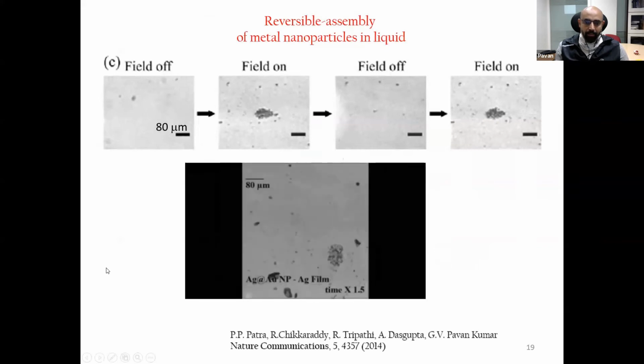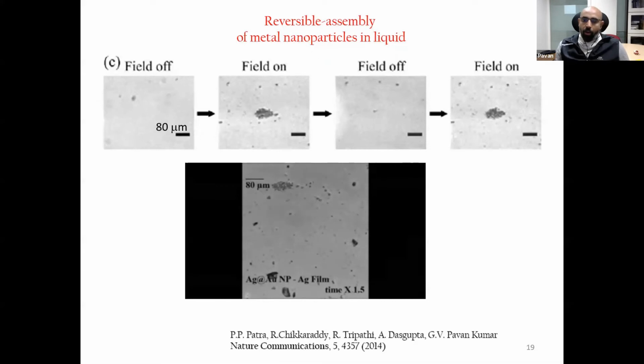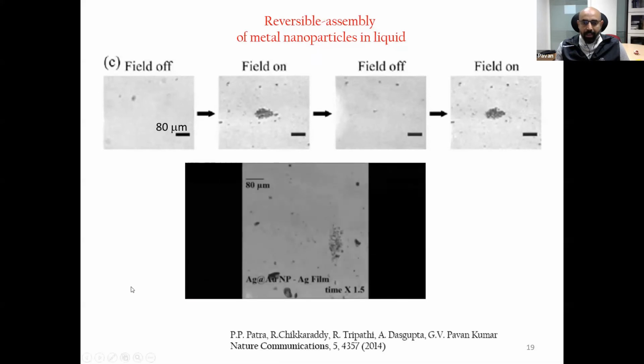Now, going further, you actually can do something more interesting. You can now play around with this assembly, where you can take this assembly and move it around at a location of your interest. Now, this is very important if you are doing, let's say, a microfluidics experiment where you want to assemble nanoparticles and then move them around as a function of space and time without having to structure the microfluidic assembly itself. So therefore, it creates some very interesting opportunities for assembly and manipulation of such kind of nanoparticle clusters in an optothermal field. Now you can reversibly switch on and off such kind of assembly. That is, of course, an advantage.